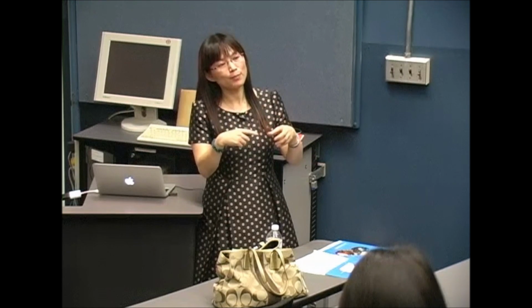Another kind of RRAM is based on oxygen vacancies. They don't necessarily use this kind of metal for the electrode. But for us, we chose the other. This is one reason. Another reason is that this kind of device makes it easy to confirm the filament by TEM. If we use the other device, like the oxygen vacancy-based device, you cannot use TEM to confirm the filament, and we are still interested in confirming it.